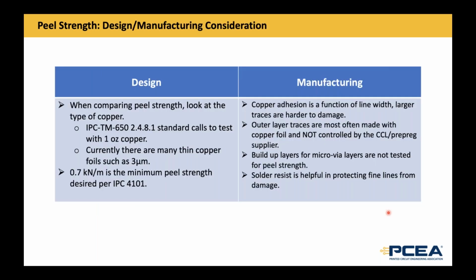All right, and lastly, I know a lot of engineers, and I've personally interfaced with customers, saying, hey, I'm using this material, crossing this one, and they just compare all the properties to make sure they're comparable. But when you are looking at the peel strength, the IPC standard calls to test with 1 ounce copper. But a lot of times, especially with all the ultra thin coppers out there, like microthin, that are less than 3 micron, the test results are going to be different. So just look at the values, and it could be lower because it's not an apples to apples comparison. Something to think about.